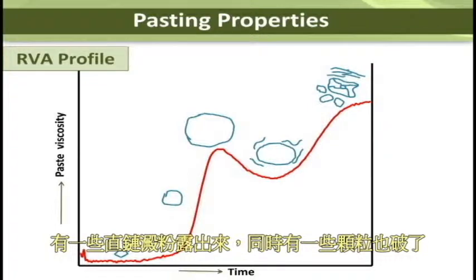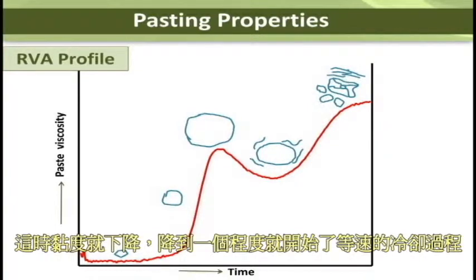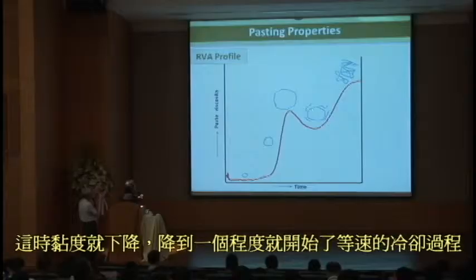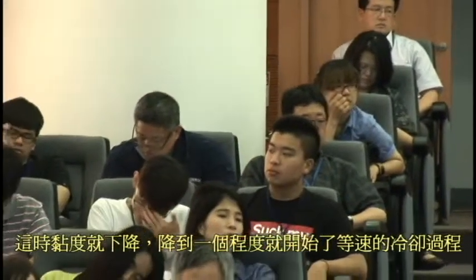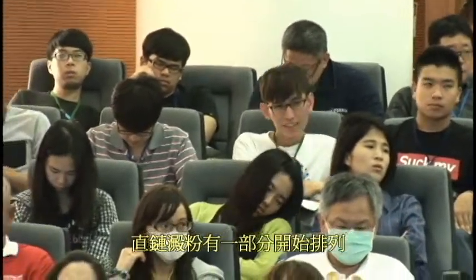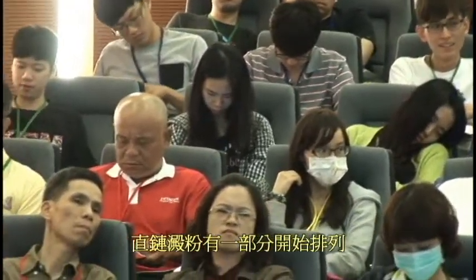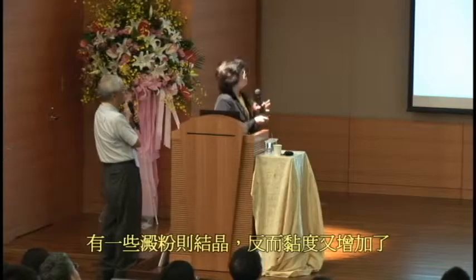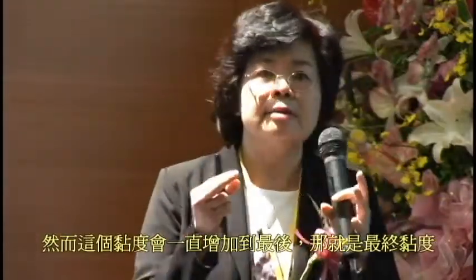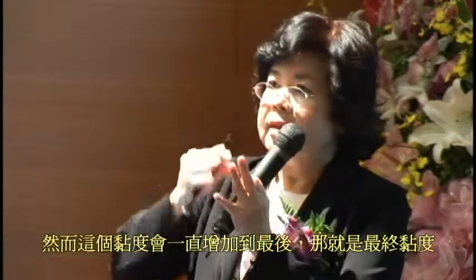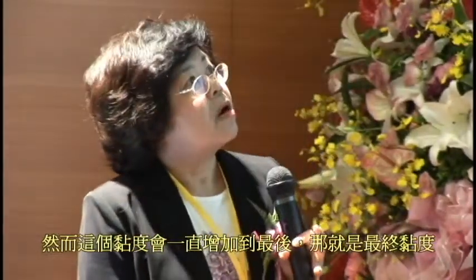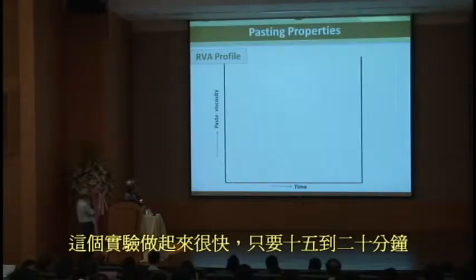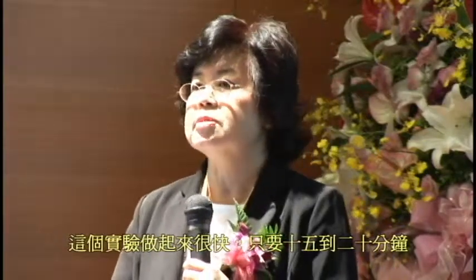After that, we still heat it at the holding temperature. Some of the amylose leaches out and some of the granules disrupt, so the viscosity goes down at the end of the heating period. After that is the cooling period. The amylose chains align together during the cooling, and some of the granules or the fragments of the granules, disrupted or undisrupted, align together during the cooling. That causes an increase in viscosity. The whole process takes about 15 to 20 minutes, so it's quite fast.